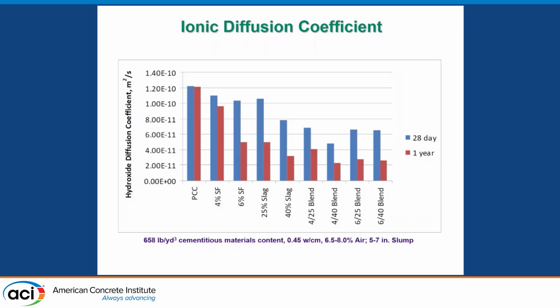And here's the ionic diffusion coefficient as well. Again, just a little bit different way to look at this. And again, you're seeing very low values when you're looking at the 1 year. So here, a 4 and 40 blend. So when I start looking at how I'm going to make my mixtures, especially for bridge decks and pavements, I'm looking for these longer-term solutions rather than just a quick fix.